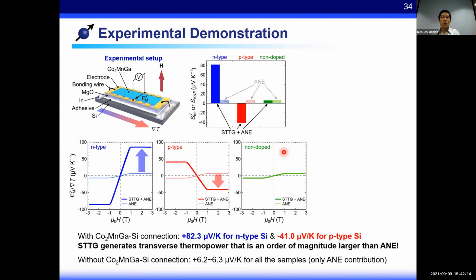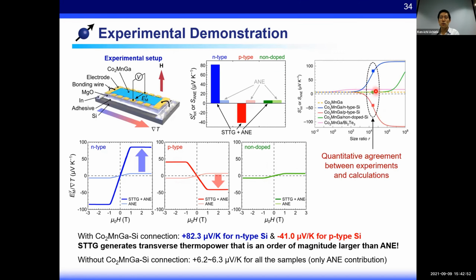When the CMG layer was connected to the silicon substrate at the ends of the sample, a large transverse thermal power of more than 80 microvolt per Kelvin was observed when the N-type silicon was used. The sign of the thermal power is reversed when P-type silicon with the opposite sign Seebeck coefficient was attached. When the magnetic thermoelectric layer is highly resistive, the obtained thermal power was not affected. All the experimental results are quantitatively consistent with our phenomenological calculations. These plots are the experimental results, and these curves come from the phenomenological calculation. This consistency confirms the appearance of the STTG contribution.